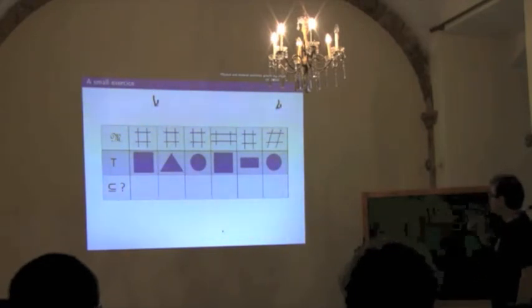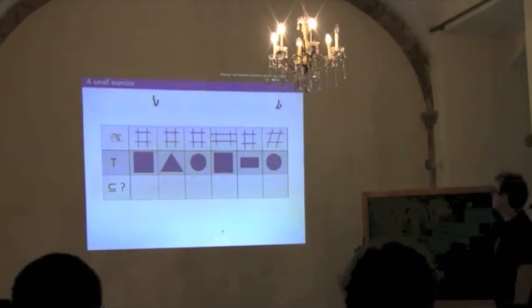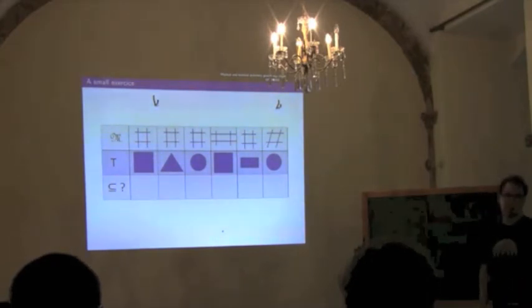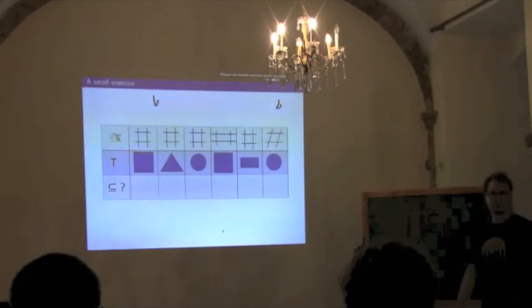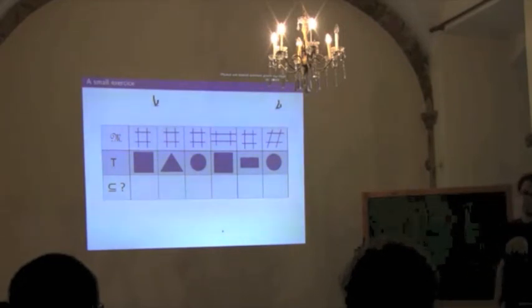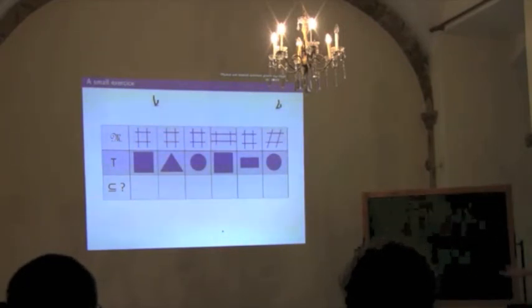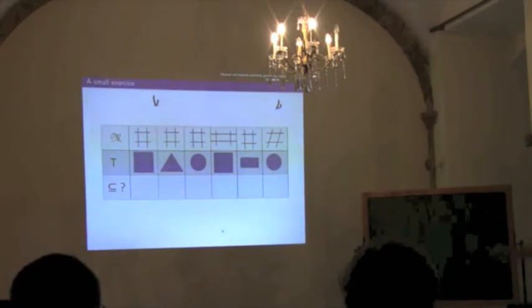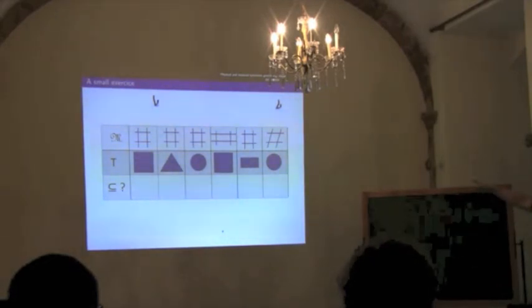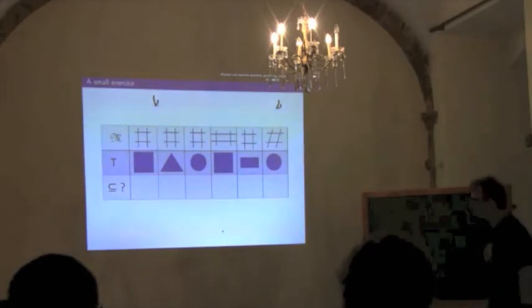For the fourth column, my matter is invariant by D2, and my physical property is invariant by D4. That's fine. Your physical property can be more symmetrical than your matter, because any operation that leaves your matter invariant leaves your physical property invariant, so no problem.